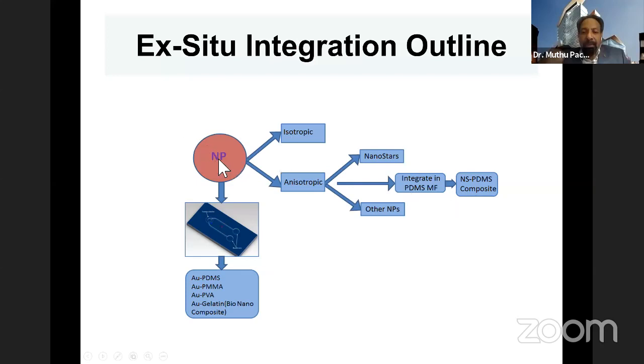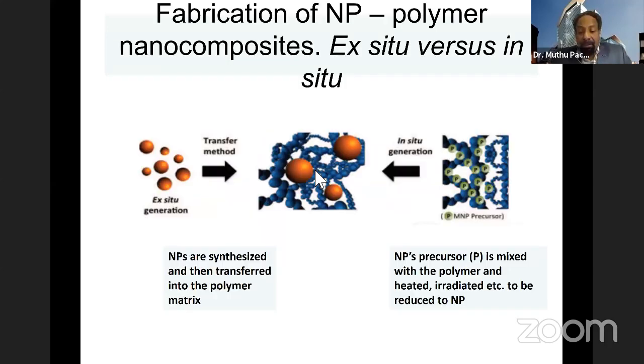So in the case of ex situ synthesis, you see, we produce nanoparticles of different sizes, and those nanoparticles are available, then we immobilize them into these microfluidic channels, and we have sensing platforms or sensing substrates of different materials. So you can see here the nanoparticles, when they are made outside and immobilized into this polymer matrix, that is an ex situ synthesized nanocomposite, or the precursor of this nanoparticle can be made to react with this polymer matrix, and then we can make in situ synthesis of gold nanoparticles.